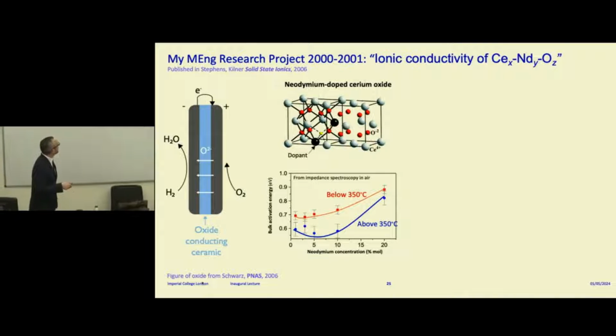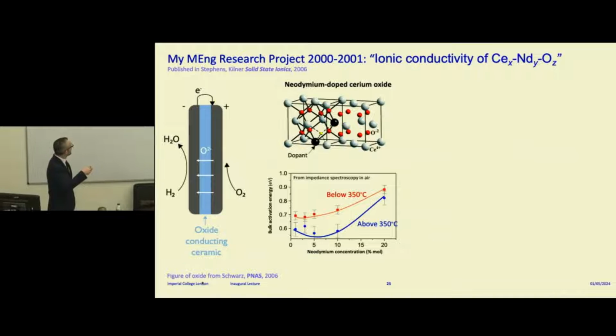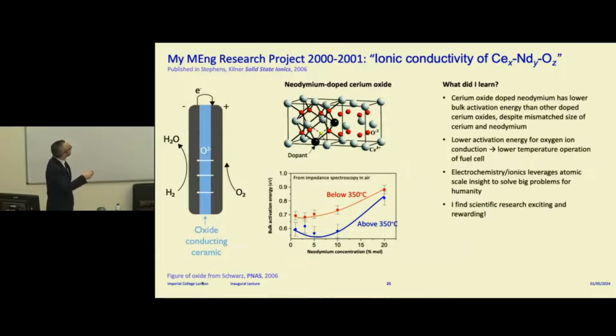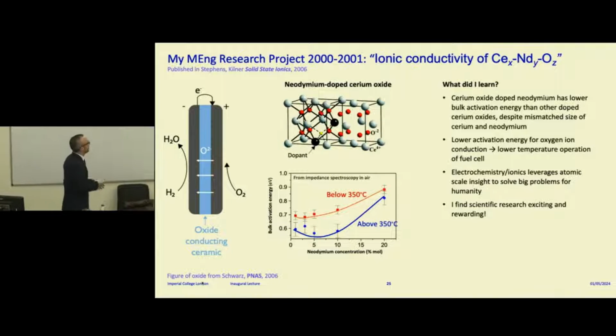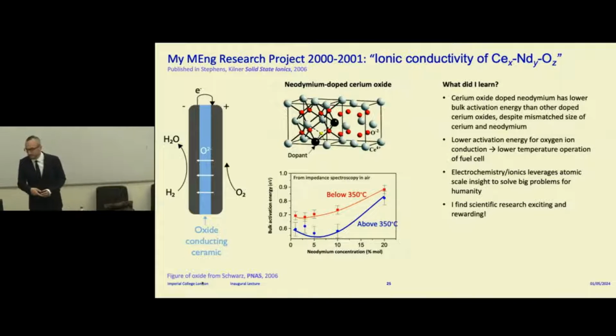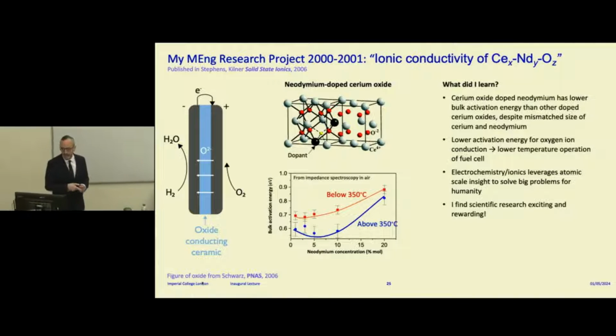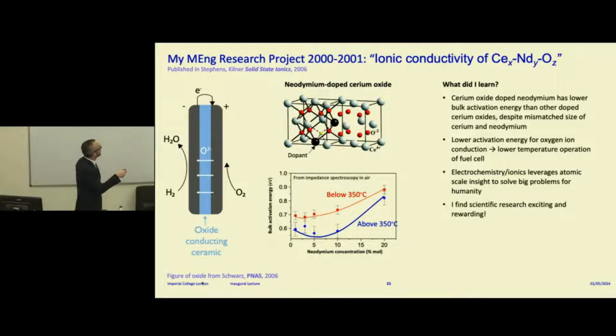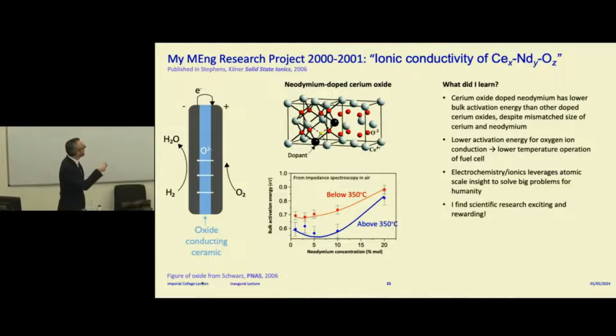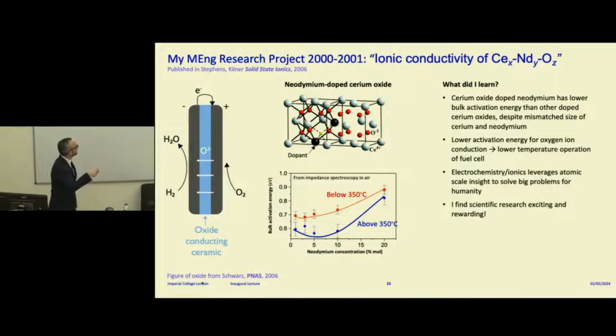And what we found is actually that the activation energy was lower than what people had reported for any other materials. And it was slightly counterintuitive, because neodymium has a slight size mismatch with cerium oxide, and people usually thought you need to minimize the size mismatch. So this is exciting for me. So in principle, if you could optimize it further, you could even use it eventually in a fuel cell. It hasn't happened, but there was hope at the time.